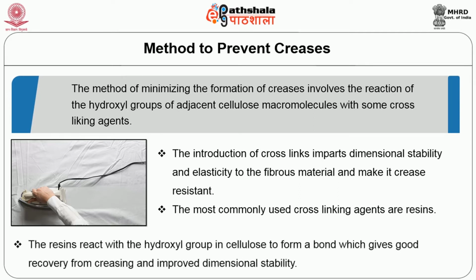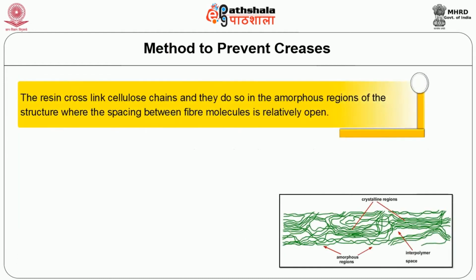The resins react with the hydroxyl group in cellulose to form a bond which gives good recovery from creasing and improved dimensional stability. The resin cross-links cellulose chains, and they do so in the amorphous regions of the structure where the spacing between fiber molecules is relatively open.